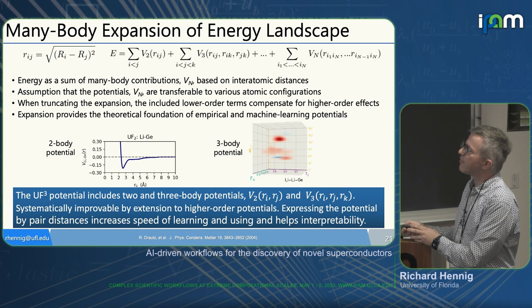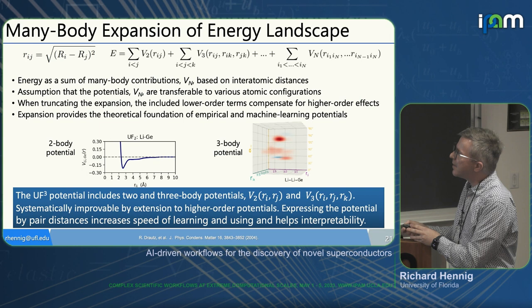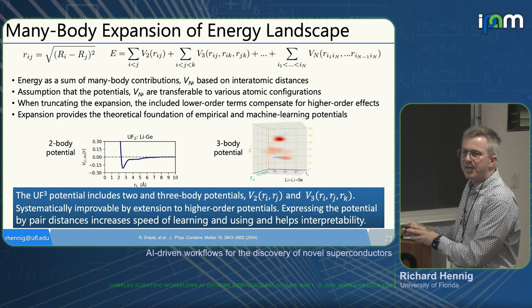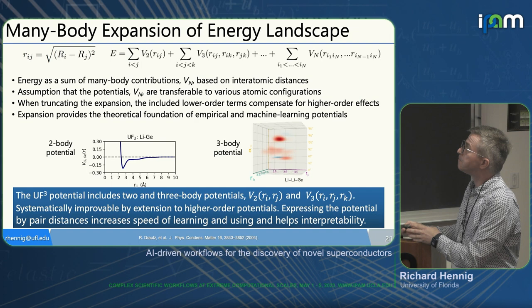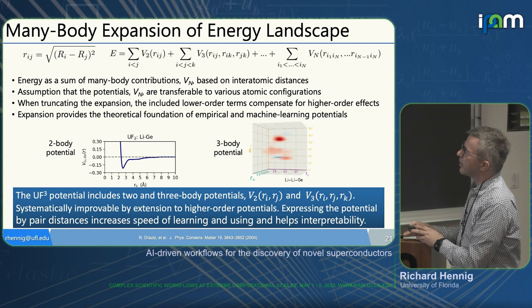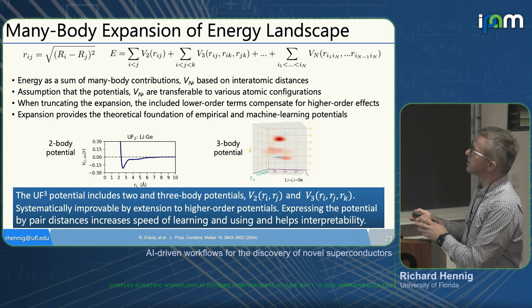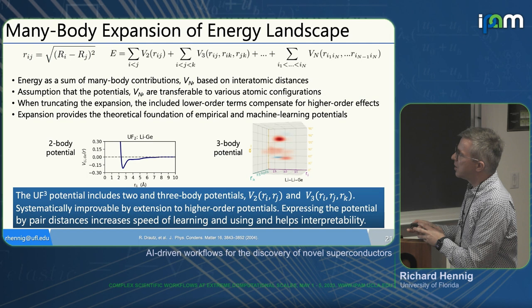We're using a many-body expansion: a sum of two-body terms, three-body terms, all the way to n-body terms. We've really only tested the two and three-body terms ourselves. We expand the two-body potential in a linear sum of B-spline basis functions as a function of distance. The cubic B-spline basis has local support — for every distance, I only have to evaluate four B-splines, so cost is completely independent of resolution. Making the knots closer together still requires only four B-spline evaluations per distance. They have a smooth first derivative for forces and a continuous second derivative for phonons.